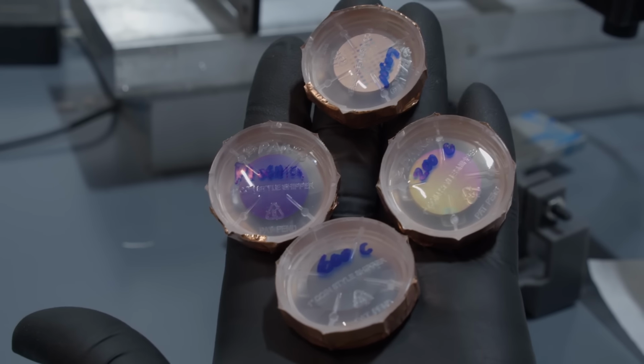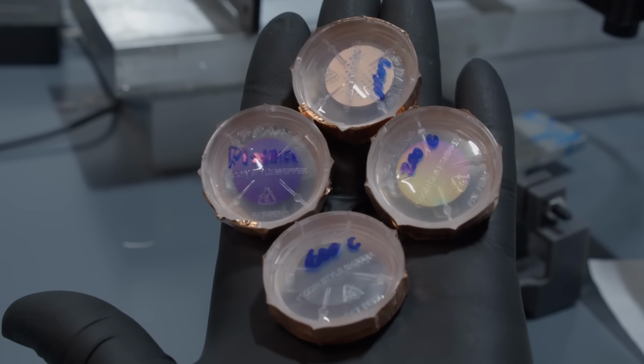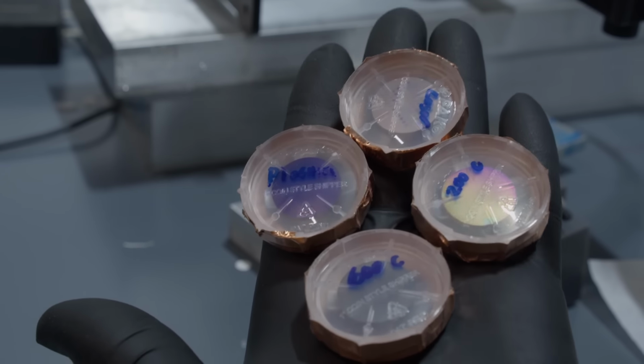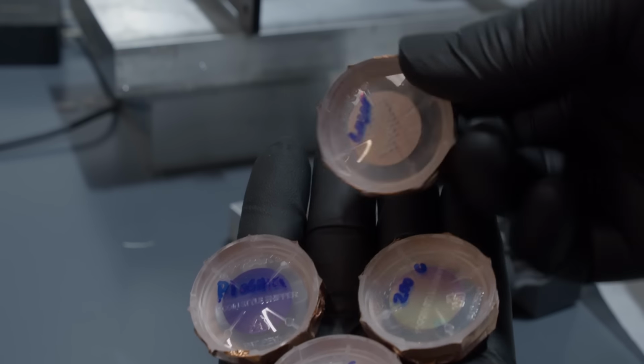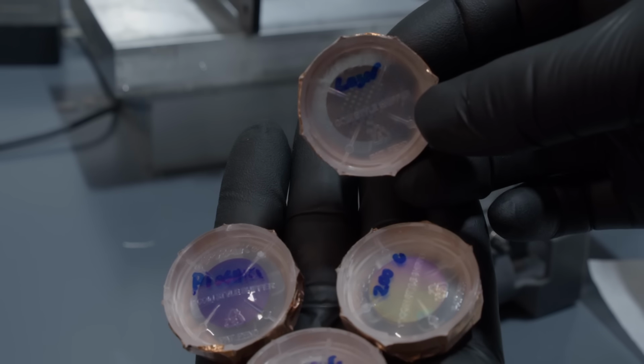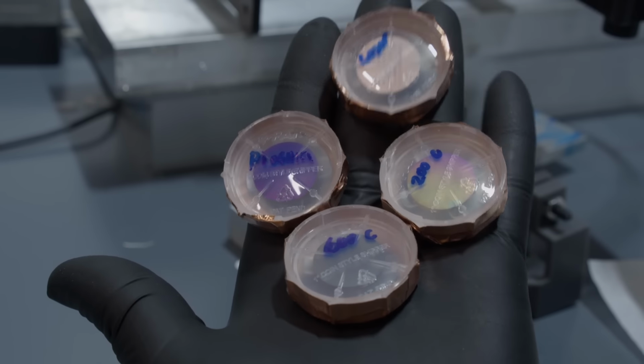Now, Molecular Vista warned me about potential sample contamination. I had to package up the samples in specific wafer carriers and only use acrylic-based metallic tape. The microscope is just so sensitive that it can pick up contaminants like silicones outgassing from nearby adhesives. Silicones and silanes are everywhere and stick to most surfaces, so we had to be really careful about sample prep and packaging to ensure that we got good results.